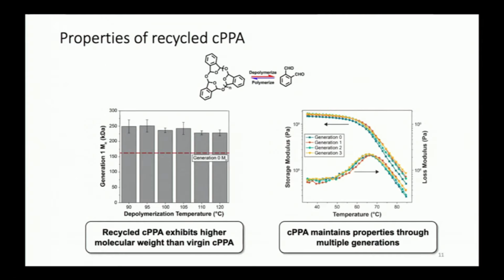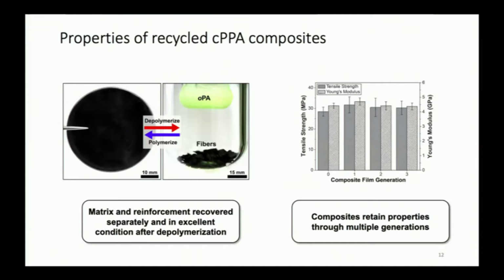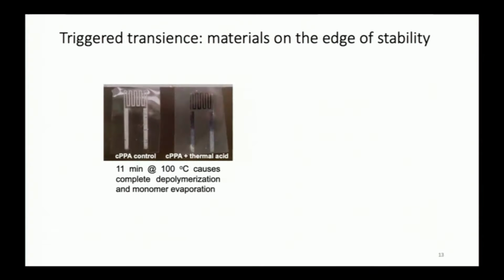So that's really a simple-minded approach. You wonder whether this material could actually then be put into these composites. A composite is about 50% polymer. It's often a thermoset, but here we're using a thermoplastic, that cyclic poly(phthalaldehyde). And you can indeed go through the process generation after generation, recover the monomer, and then measure the mechanical properties, and they're largely unchanged. So you can, with almost complete quantitative recovery, get that high yield.